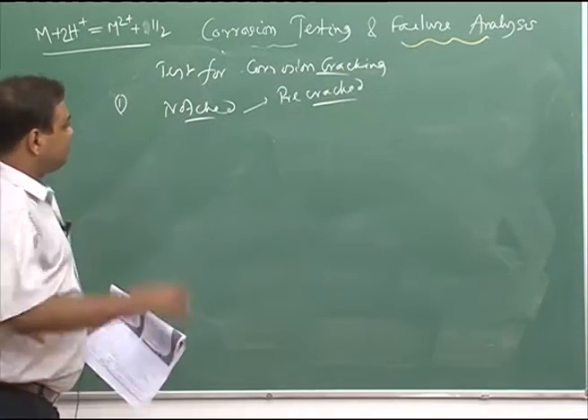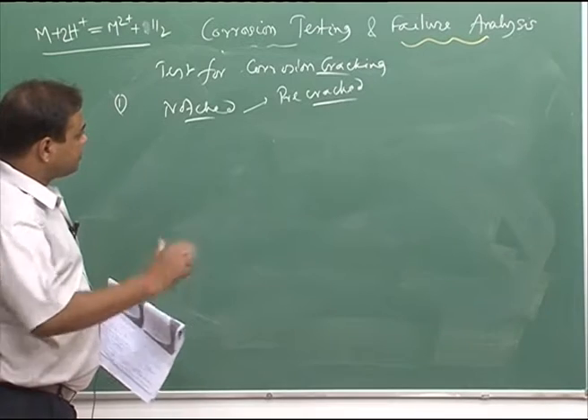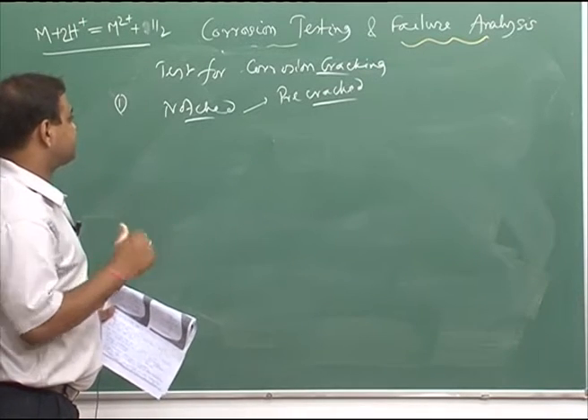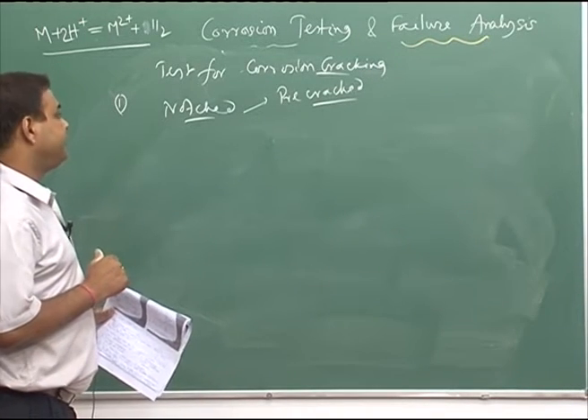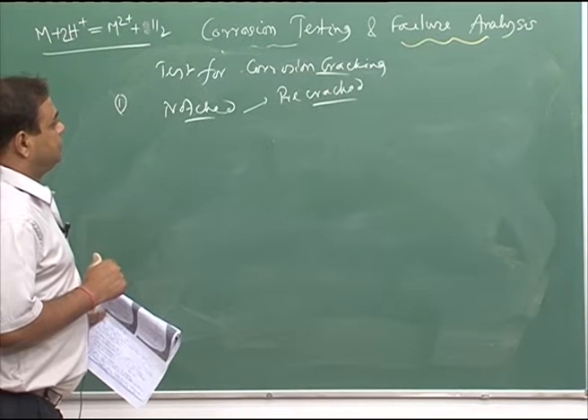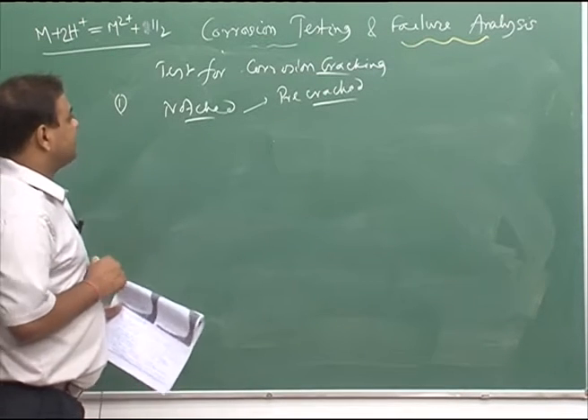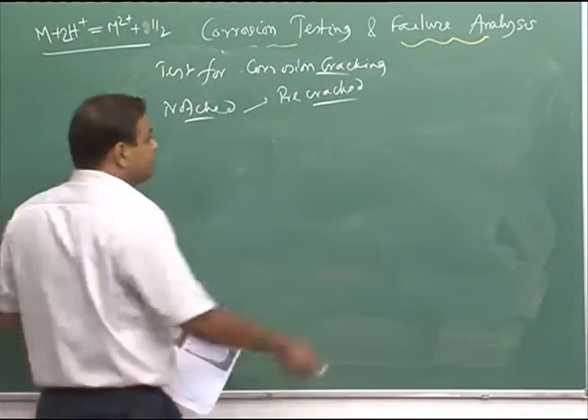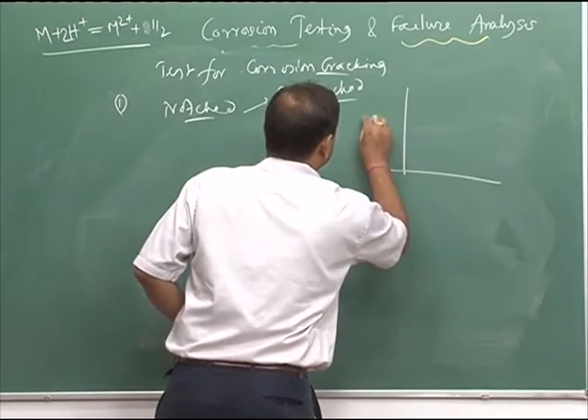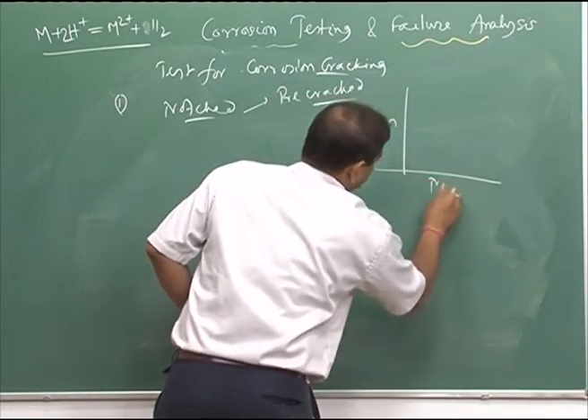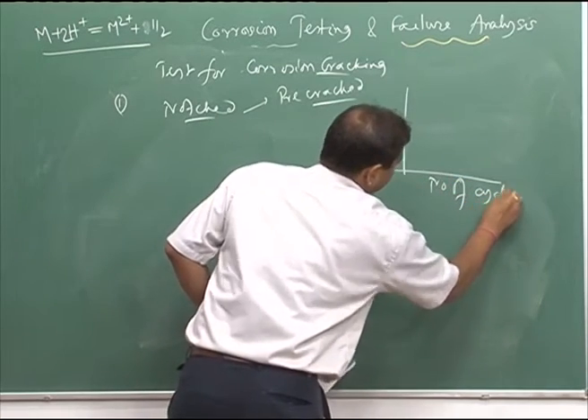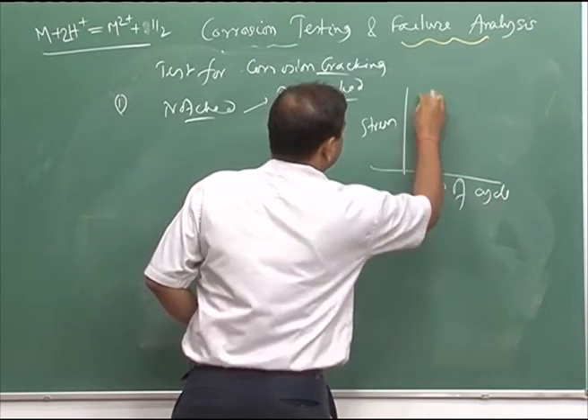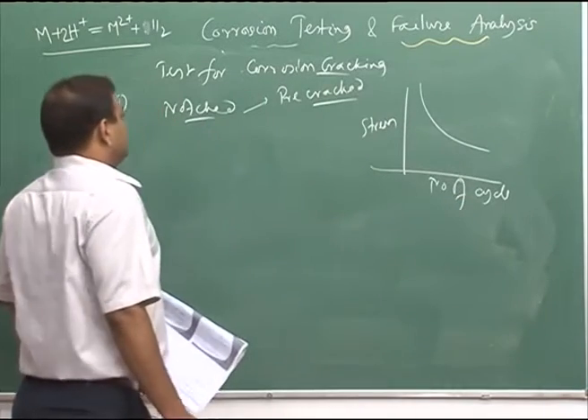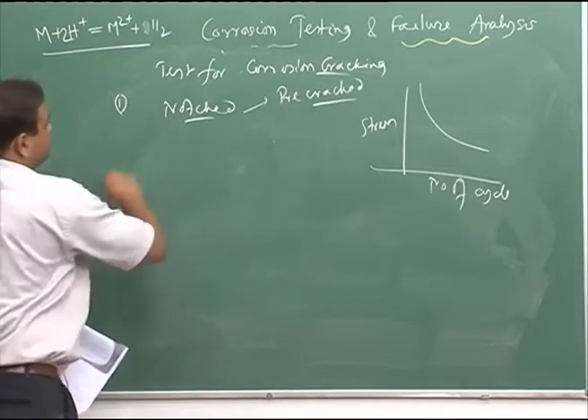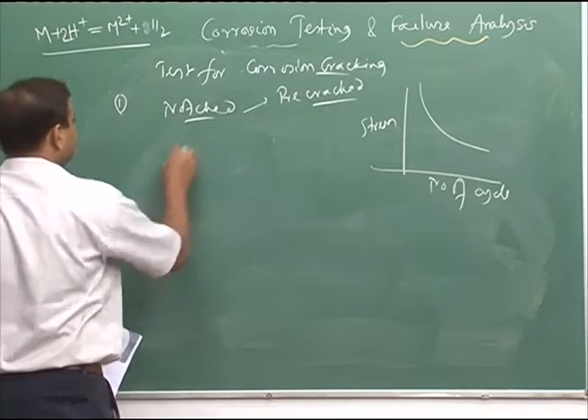A pre-cracked sample, if we put it in solution and rotate it and give a certain stress, we can find out the corrosion fatigue susceptibility of the metal, and we can get a plot of stress versus number of cycles. So we can have a plot like this. Now, this is for corrosion fatigue.